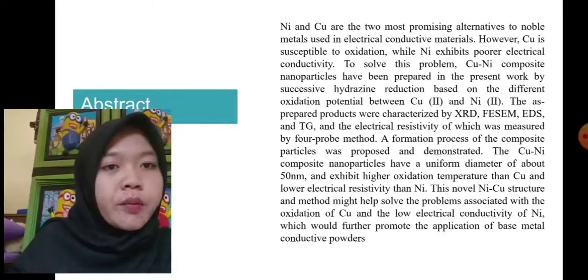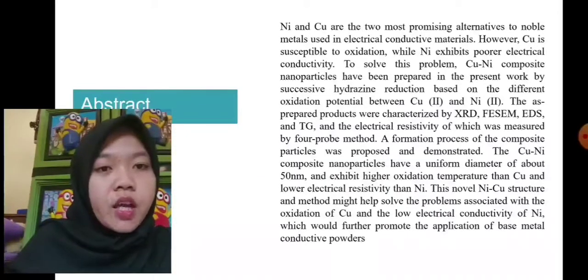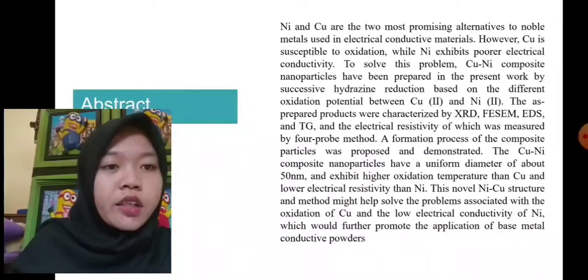The as-prepared products were characterized by XRD, FESEM, EDS, and TG, and the electrical resistivity of which was measured by the four-probe method. A formation process of the composite particle was proposed and demonstrated. The copper-nickel composite nanoparticles have a uniform diameter of about 50 nanometers and exhibit higher oxidation temperature than copper and lower electrical resistivity than nickel.